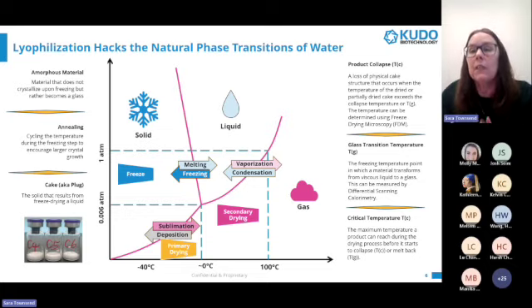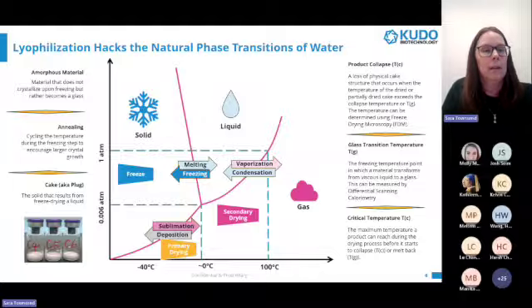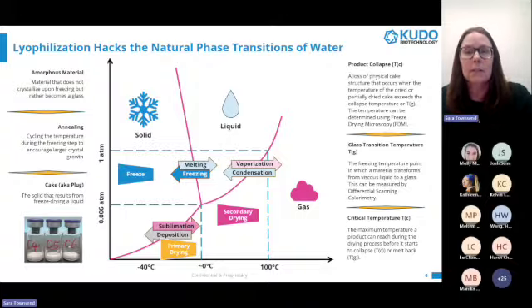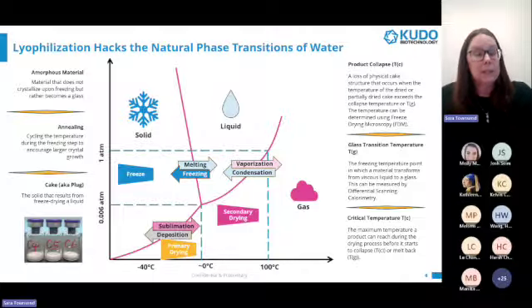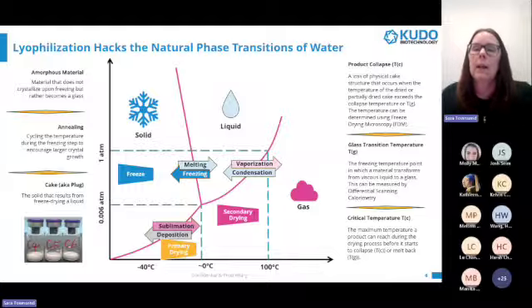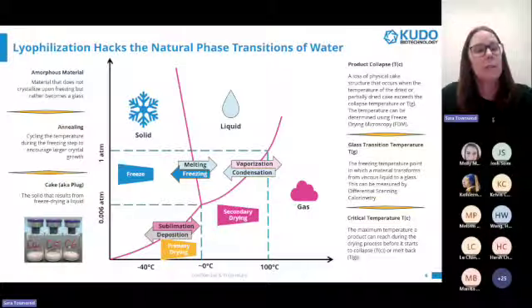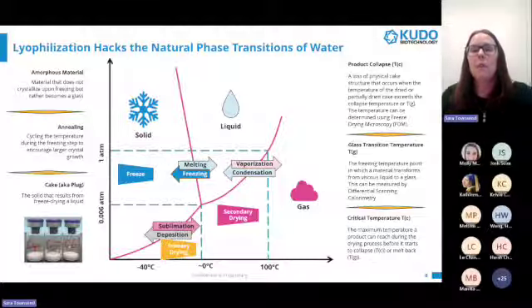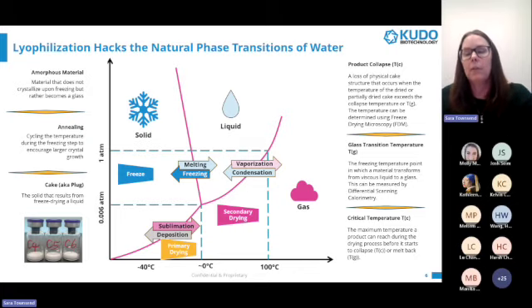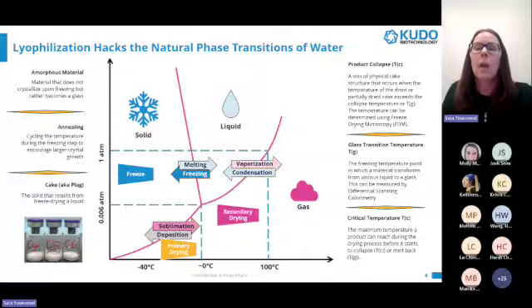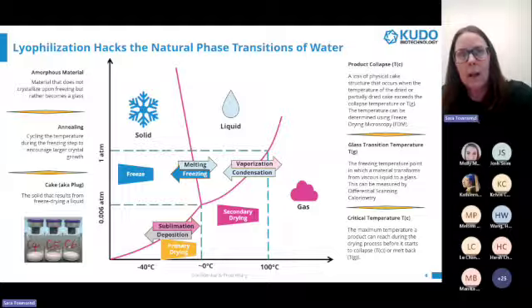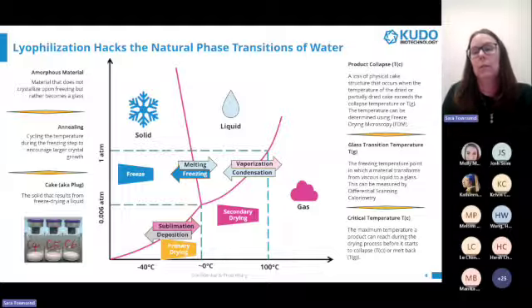Some additional terms that are specific to lyophilization include cake, this here. This is the final solid that is obtained after removing the liquid from the material. This material may be amorphous or crystalline. However, most drug products are amorphous and will freeze into a glass instead of a crystal form. The temperature that this happens is called the glass transition temperature. And this temperature is influenced not only by the drug product, but the buffers and other excipients present. Knowing the critical temperatures, such as the glass transition temperature and the collapse temperature, is essential in order to ensure a successful lyophilization of the drug product.